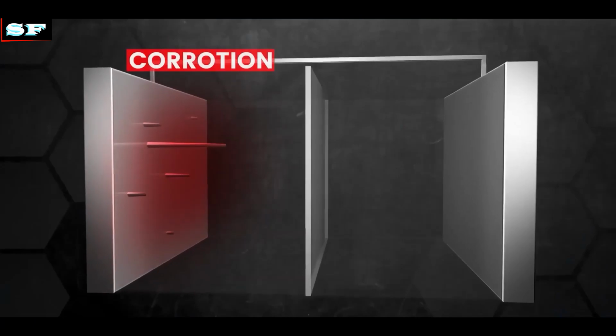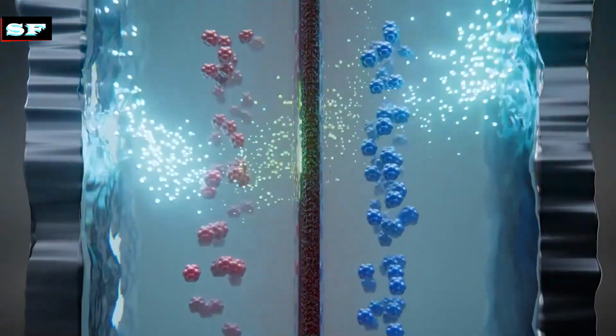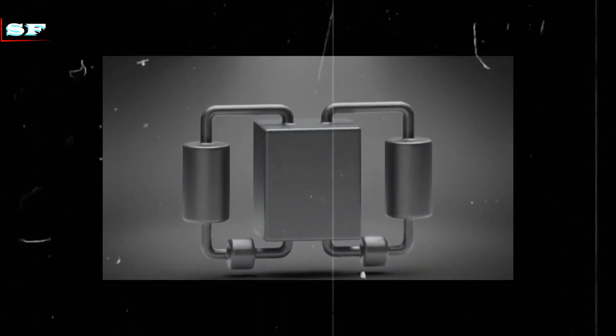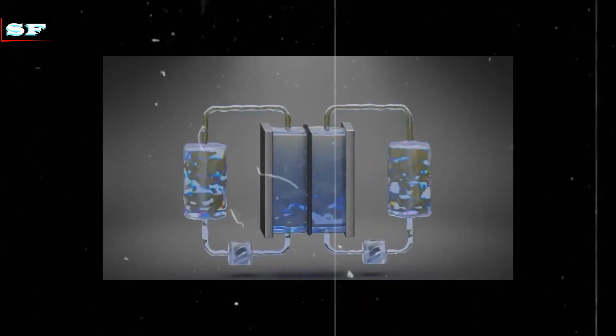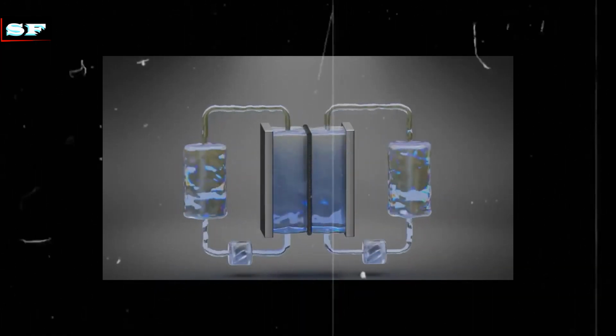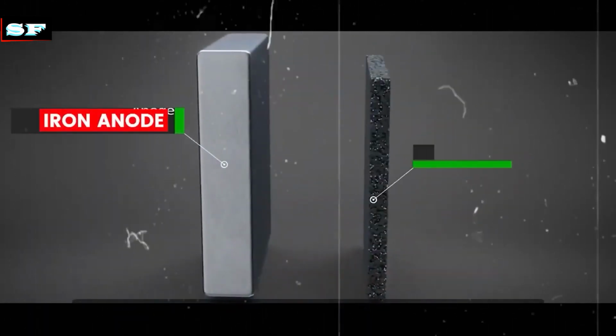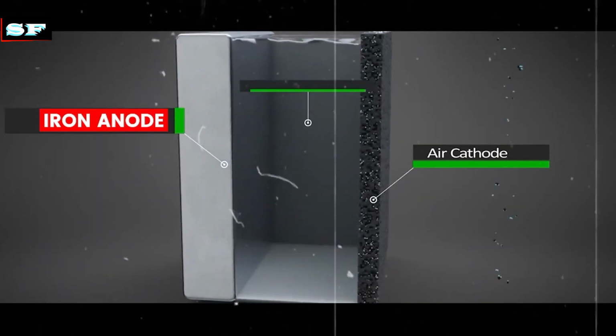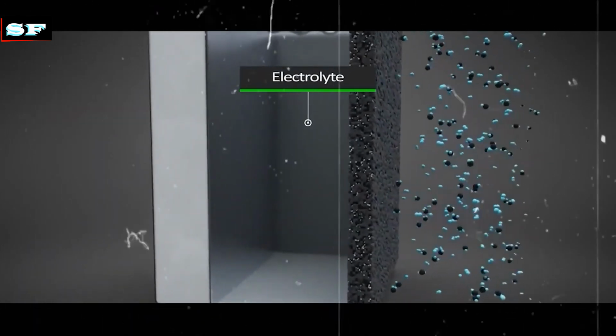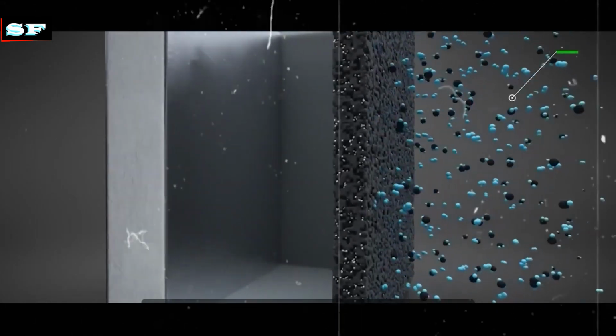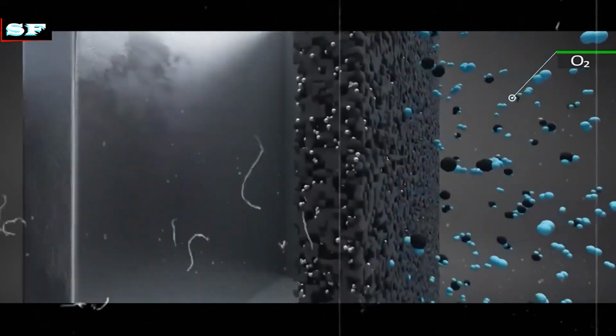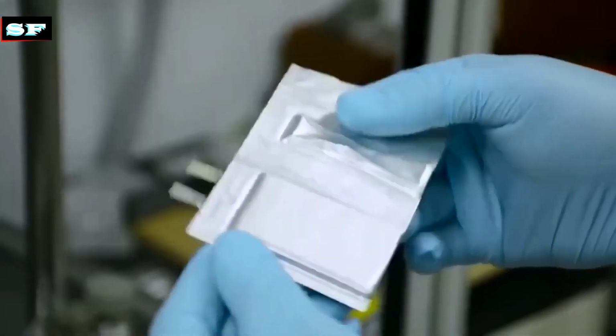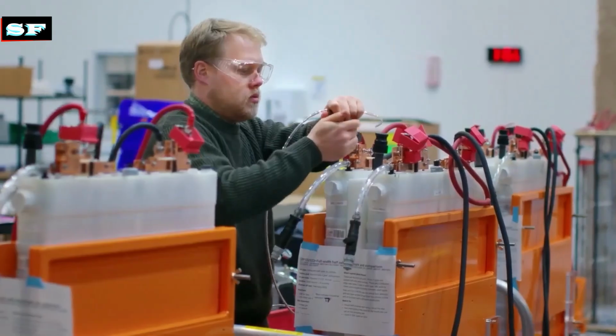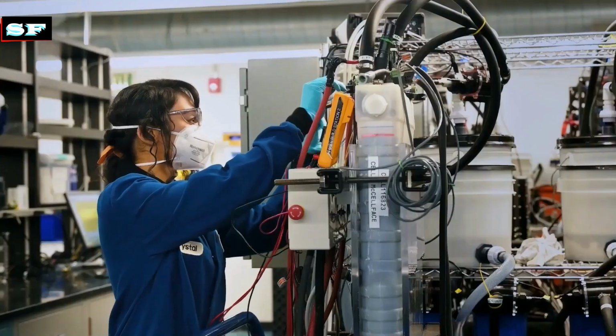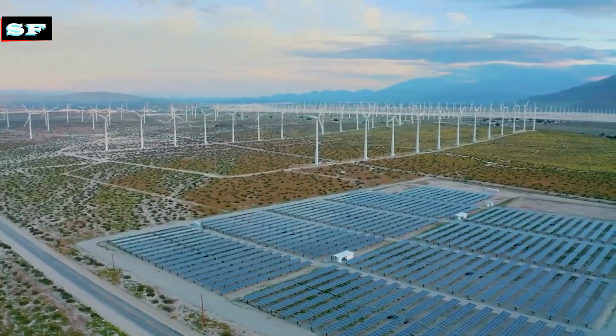Further, this battery chemistry may be susceptible to anode corrosion, cathode clogging, and cathode poisoning from contaminants in ambient air. And unlike lithium-ion batteries, an iron-air battery has additional system complexity and balance of plant requirements for the air cathode. Iron-air batteries also have a relatively low power density and poor rate capability, which means they are not well suited for applications requiring rapid discharge. For these reasons, the majority of the capacity of an iron-air battery would not be accessible for diurnal cycling and would likely only be fully utilized a few times per year, severely restricting their applicability.